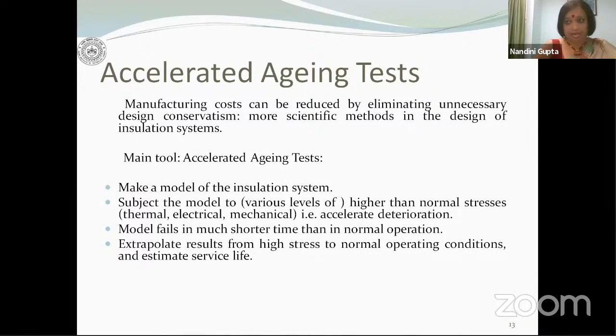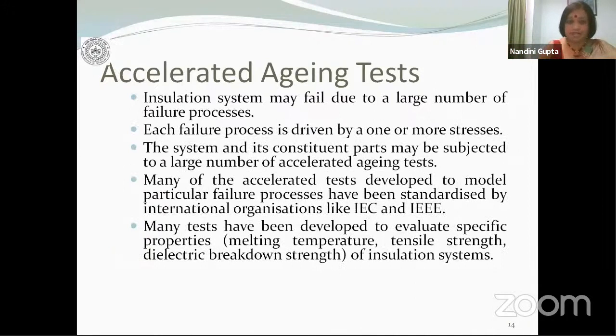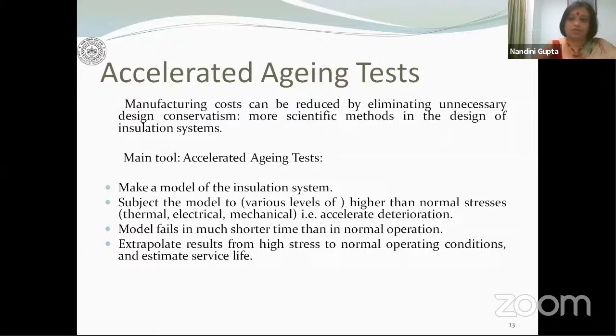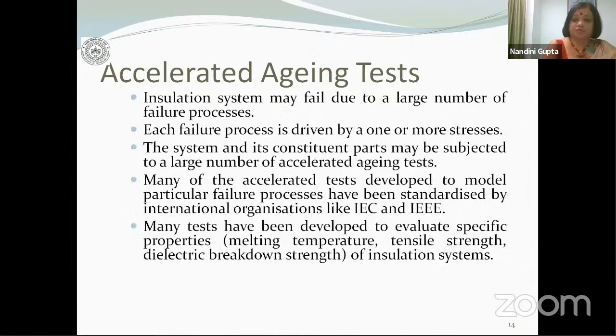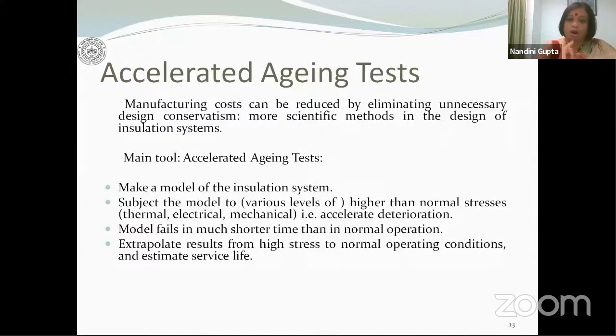If you are looking at electrical stresses, if you expect that under normal conditions you expect 30 kV per centimeter, and even if the overvoltages that you expect are, let's say, 40 kV per centimeter, I'm just giving values, don't pay any attention to them. If you're expecting 30 kV per centimeter and you are expecting your insulation to last 30 years, what you do is you go to much higher stress levels, maybe 150 kV per centimeter, and see what is the time to breakdown in this situation. So you are going to accelerate the deterioration process.